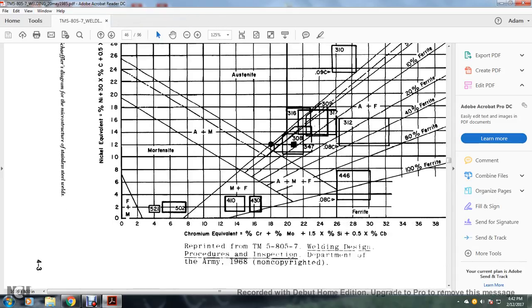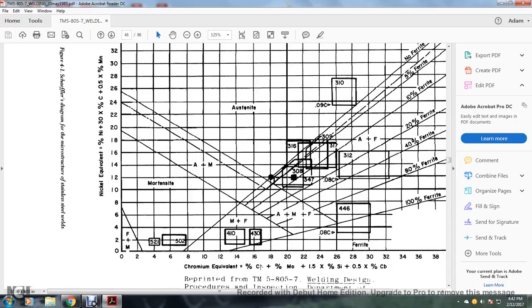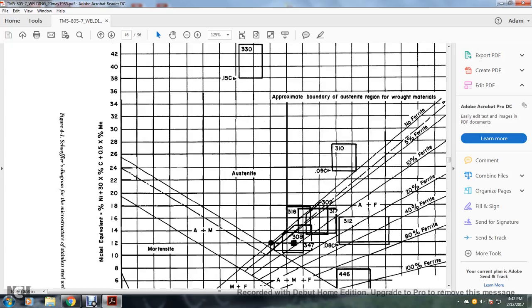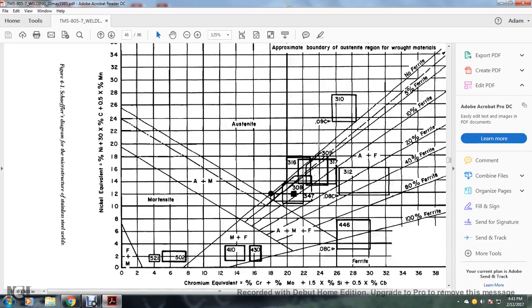Let's rotate the picture. You have your Reprinted from Technical Manual 5-805-7, Welding Design, Procedure and Inspection, Department of the Army, 1968 (noncopyrighted). Chromium equivalent is the percentage of chromium plus the percentage of molybdenum, plus 1.5 times silicon, plus 0.5 times columbium, versus nickel equivalent, the percentage of nickel plus 30 times the carbon and 0.5 times the manganese. These are approximate borderlines. Regions: martensite, austenite, and ferrite at 0, 5%, 10%, 20%, 40%, 80%, 100%.